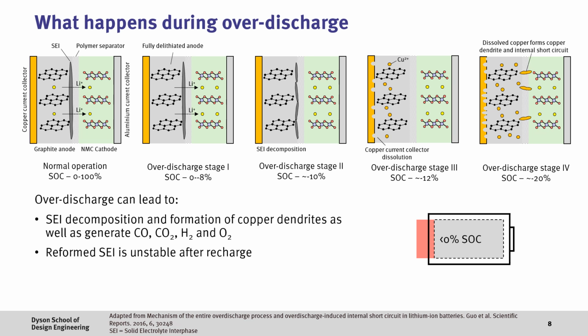Therefore, over-discharge can lead to the decomposition of the SEI layer and formation of copper dendrites, as well as generate gases such as carbon monoxide, carbon dioxide, hydrogen, and oxygen. Now, in most cases, a battery can be recharged after over-discharge. However, the reformed SEI in general is less stable, and there's increased risk of failure due to potential copper dendrites.